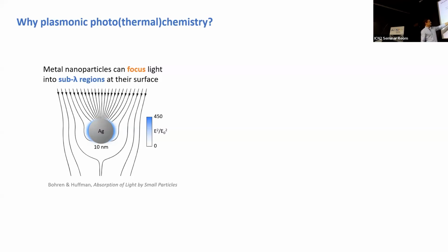What I'm plotting here is the usual silver nanoparticle, 10 nanometer in vacuum, and the blue shaded areas are the electric field E squared enhancement. So E squared divided by E0 squared, where E0 is the electric amplitude of the incoming light. So I'm plotting the intensity enhancement at the surface of this nanoparticle, and you see that the electromagnetic field intensity is enhanced by 450 times in a region that is probably 1 or 2 nanometers on the surface of a metal nanoparticle.